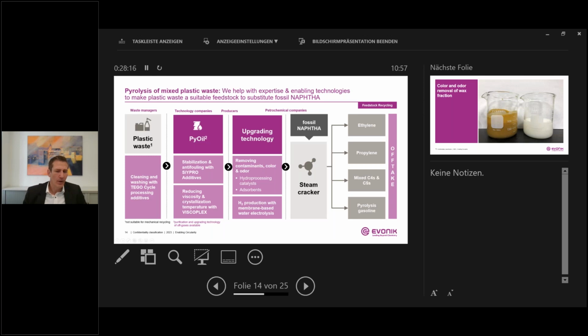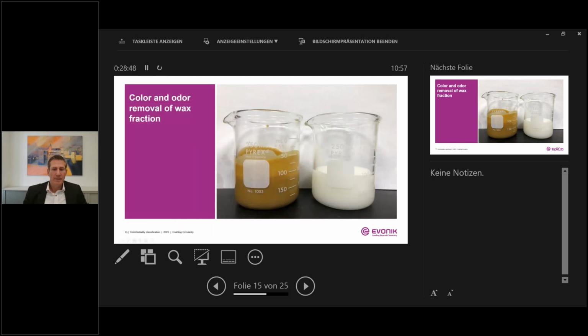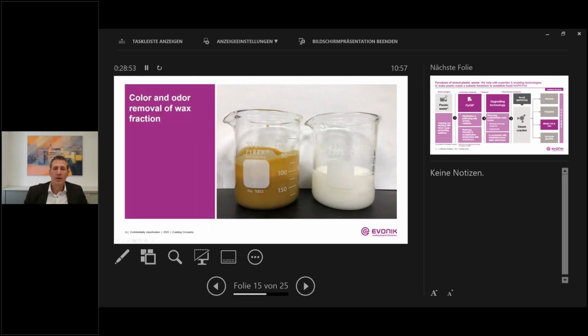And we have exactly the technologies at Evonik to remove contaminants significantly. It's hydroprocessing catalysts and adsorbent materials that are used to upgrade the pyrolysis oils, making them suitable for the steam cracker. And then, of course, you can replace the fossil naphtha. In addition, we have several other additives that are used to make the pyrolysis oil, for instance, more flowable or the storage stability better. This is a typical pyrolysis oil after it is liquefied, and we are the ones who are really removing the color. We are the ones who are really removing contaminants and therefore odor, and the result is a very pure pyrolysis wax in this picture.